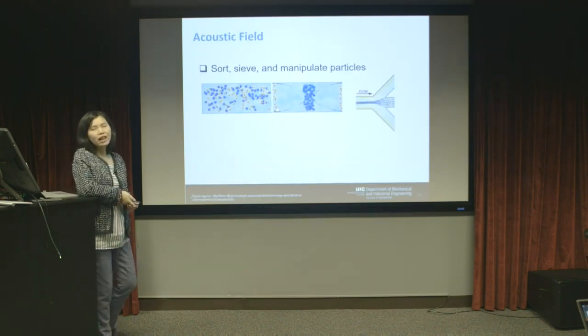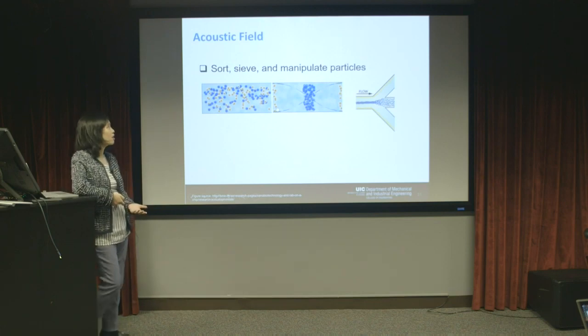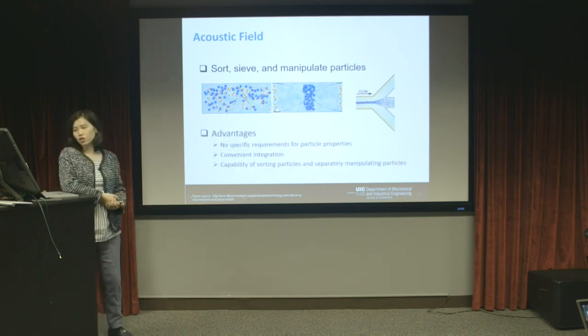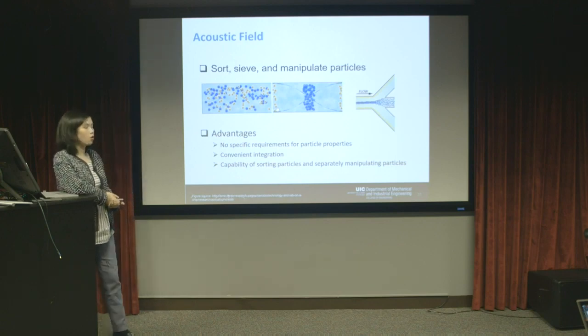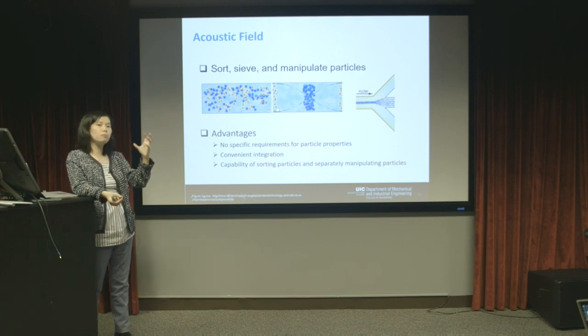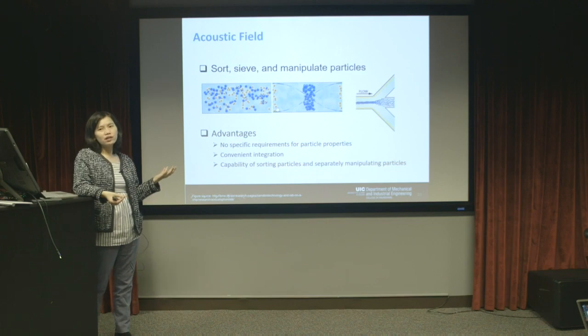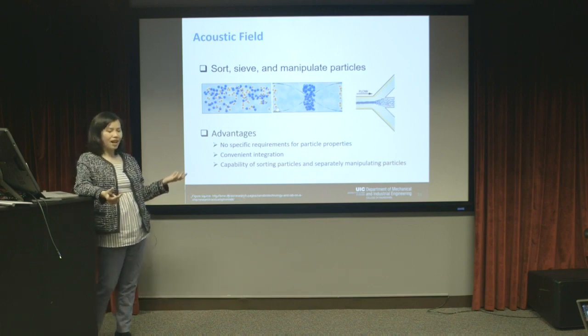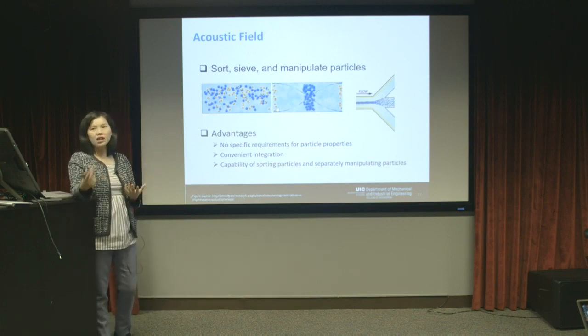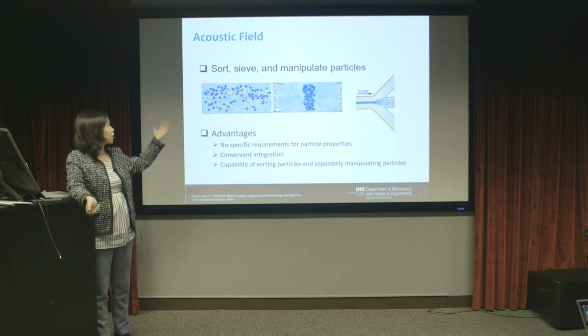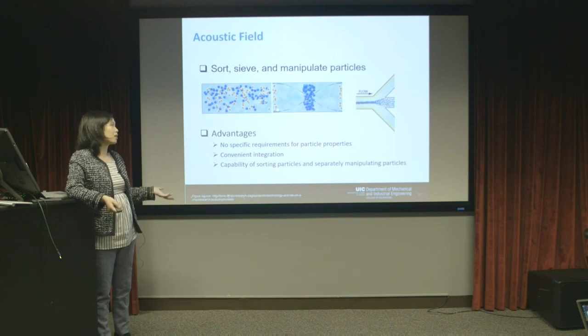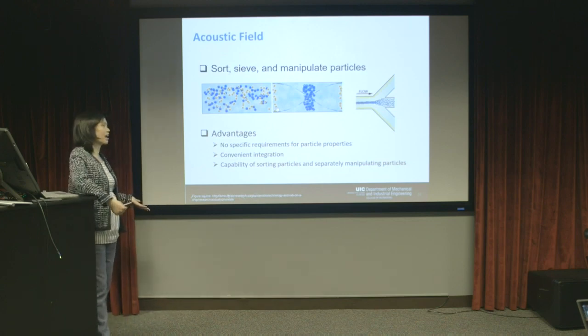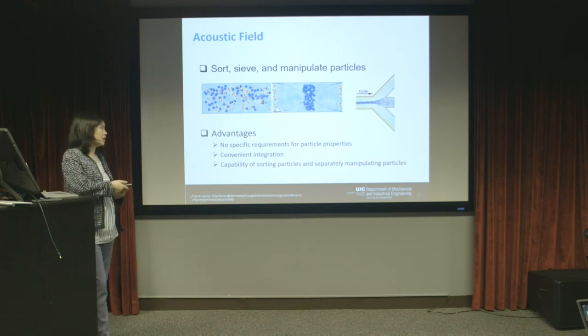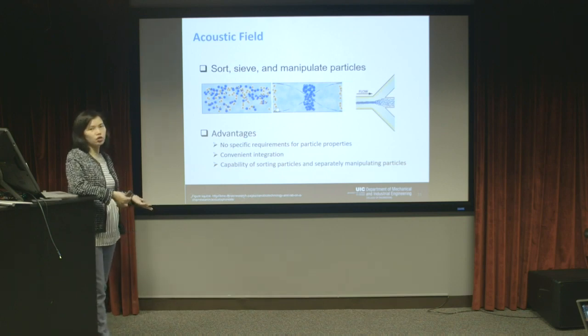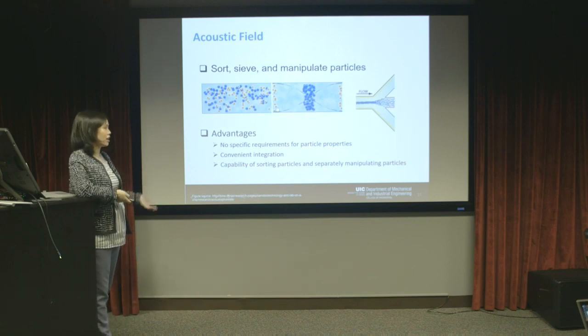So in addition to magnetic field, we can also consider other fields to be integrated into the manufacturing process, such as the acoustic field. Compared to magnetic field, the acoustic field has many advantages. For the magnetic field process, you can only control particles which are magnetic, right? Of course, if the particles are not magnetic, you can coat them to make them magnetic, but that's difficult, challenging, or time-consuming. But the acoustic force doesn't have any requirements on the physical properties of the particles. So you can control almost any particles. And it's easy to integrate into the manufacturing system because you just need some piezoelectric plates. And you can use it for sorting or separating particles.